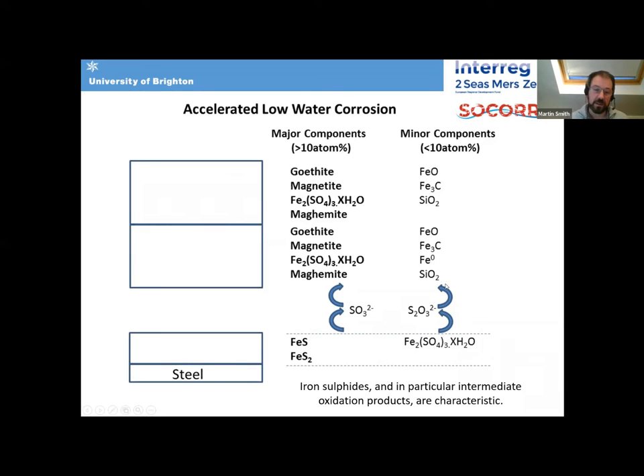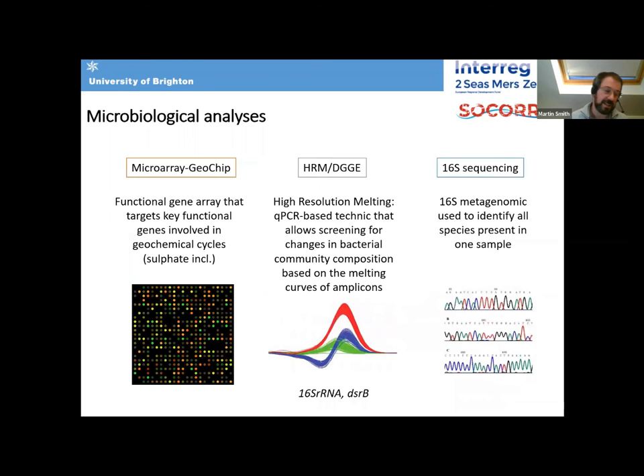Involved in that, somewhere we have amorphous phases that include thiosulfate and sulfite. And then against the steel surface, we've got iron sulfides. So we've got a really accurate picture now of what the mineralogy of these microbially influenced marine steel corrosion and accelerated low water corrosion blisters are. So what we desperately need to do then is establish what is causing that.